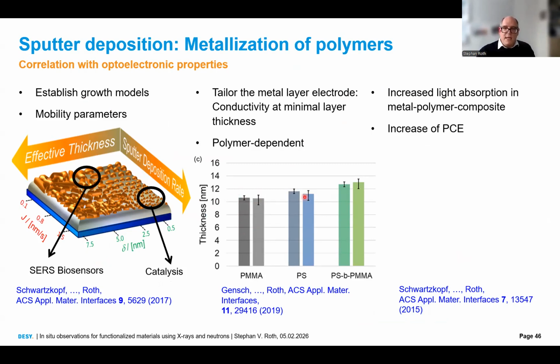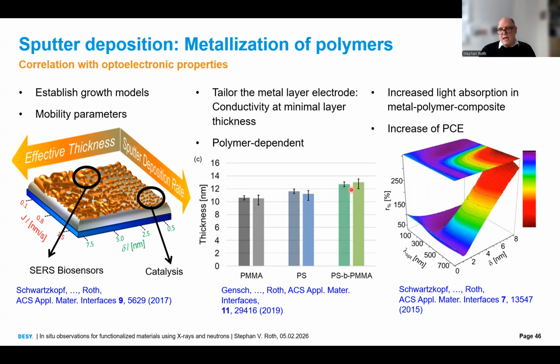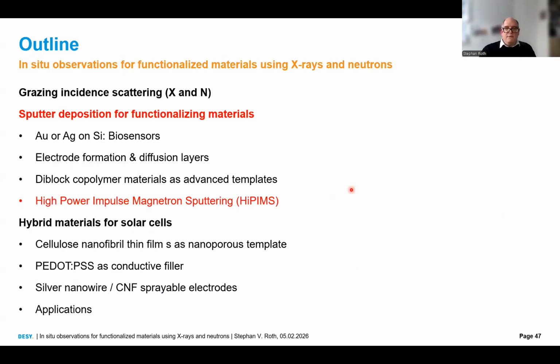And you see that our onset of electrical conductivity determined by GISAXS as well as by real measurements in the lab correspond. So we are able to tailor the metal layer electrode and determine the minimum layer thickness for conductivity, and we can even tune our absorption by small metal layers and thereby increase the efficiency of solar cells. Okay, this would be nearly the first part of my talk.